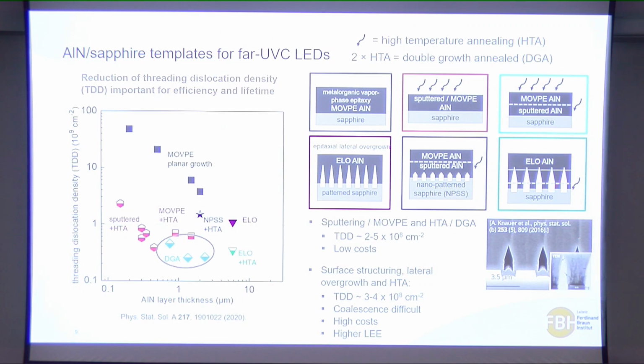So what can you do? What we have tried is sputtering a thin aluminum nitride layer, or MOVPE layer, of aluminum nitride on sapphire and then annealing it. This helps us to reduce the threading dislocation densities while still having thin layers. We don't have cracking. What works even better for us is if we do a double annealing. So we first sputter aluminum nitride, we anneal it, then we do MOVPE aluminum nitride and anneal it again.